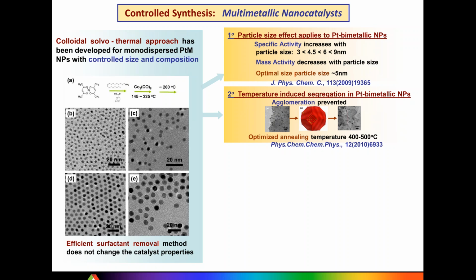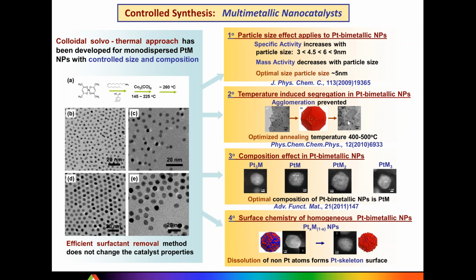So the next step was also to investigate to which extent we can rely on the appearance of the so-called platinum skin, and that was confirmed by using a number of different annealing protocols, and we found something which was the optimal temperature for nanoparticles whose average particle size was around 5 nanometers, so the optimal temperature was between 400 and 500 C. And then the last step was actually to investigate to which extent we can keep adding the non-platinum component in order to maintain those desirable properties. And it turned out that the sweet spot was around 50%, so 50% platinum, 50% alloying component.